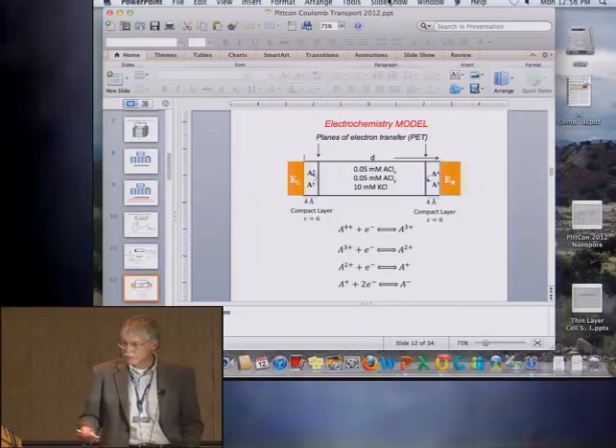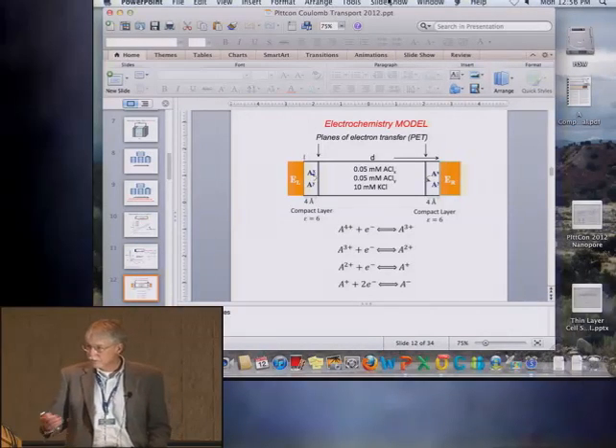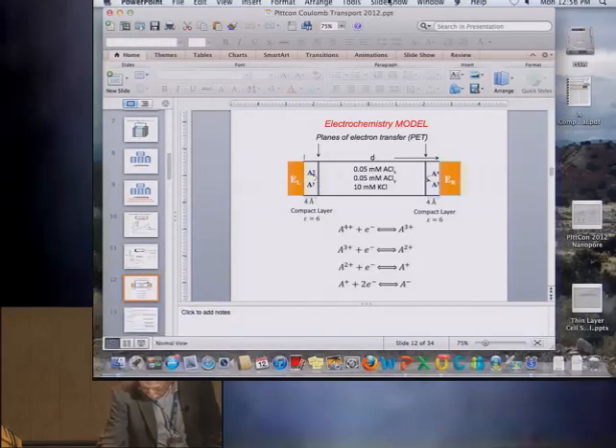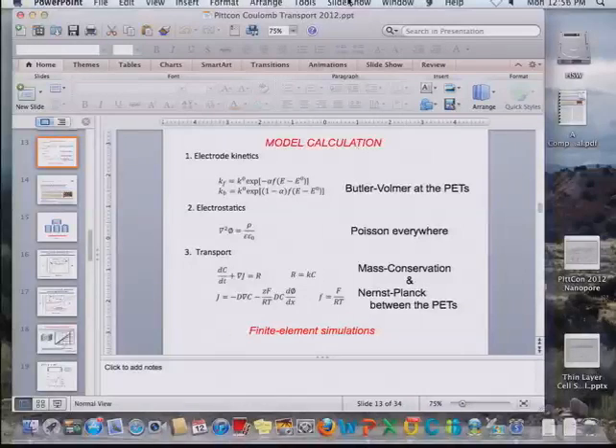If you don't put that in, you get totally unrealistic electron transfer rates because the concentration of the ions is way off. Right? So we put that in, and then we do the calculations: Butler-Volmer for the electron transfer, electrostatics as Poisson everywhere through the cell, and then transport is Nernst-Planck.